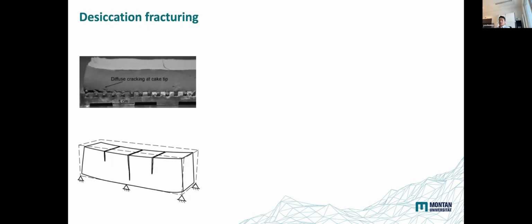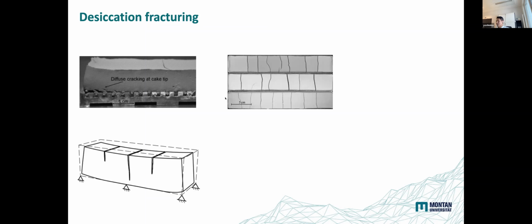Okay, and this example is about desiccation fracturing. So this was an experiment. This is a plaster, a fully saturated plaster, and this plaster was placed on top of a frictional plate. This plate has a very high friction coefficient, and then we let this plaster dry. As this fully saturated plaster dries, it shrinks, and first some crack developed on this corner, the lower left corner in this picture. And these are the images from the top. From the top, this plaster developed several vertical cracks like that.